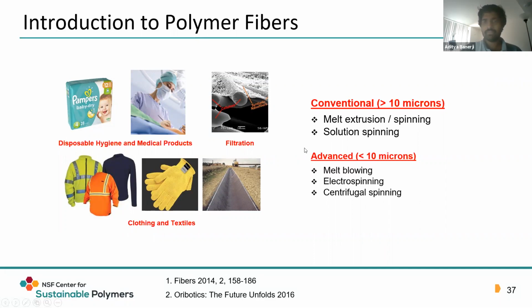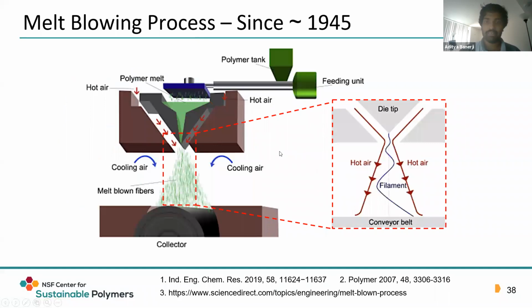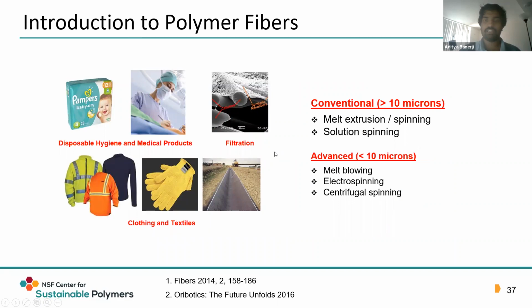Some of the techniques used to make these polymer fibers include conventional methods like melt spinning or solution spinning, in which typical fiber diameters are above 10 microns or so, while advanced methods involve melt blowing and electrospinning, where fiber diameters much less than 10 microns, even in the range of nanometers, are attainable. The major difference between the conventional and advanced processes is the way the fibers are drawn out, and also the viscoelastic properties of the polymers used in these particular processes.